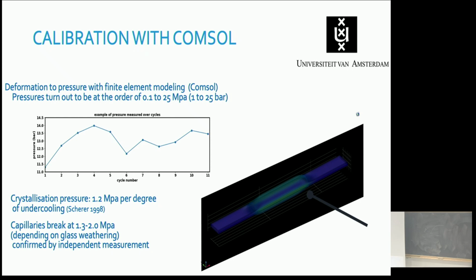And from the calculation of the chemical potentials, Scherer, some 40 years ago, already calculated that the crystallization pressure, the maximum pressure that the growing crystal could exert, is something like 1.2 megapascal per degree of undercooling. We can put compressed air on our capillaries and try to break them and measure the pressure at which they break, and we find that is roughly between 1.5 and 2 megapascals.